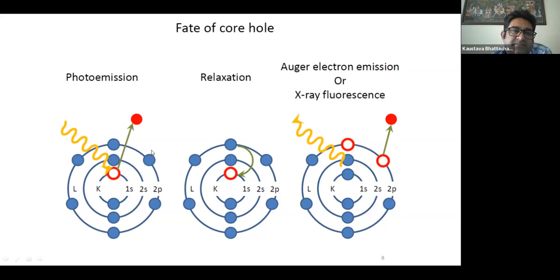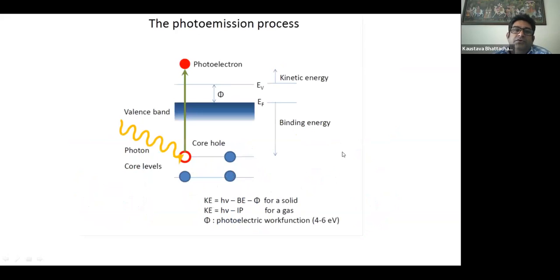So any XPS process will always have the AES process, that is Auger electron emission, along with the X-ray photoelectron emission. And the competitive route will also have an X-ray fluorescence part. So we can check the system like this. We have put some X-rays here. The electron is being ejected into the vacuum. This photoelectron is being produced, and the kinetic energy of this photoelectron is being measured by the detector. So my detector is mainly measuring the kinetic energy of this photoelectron.